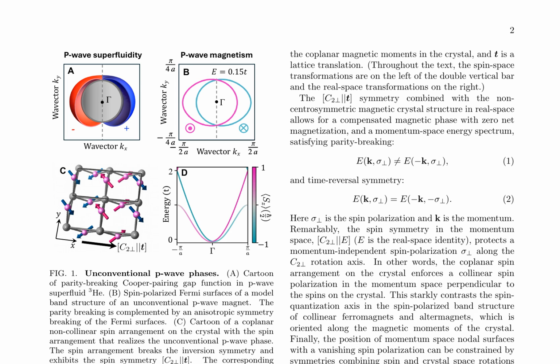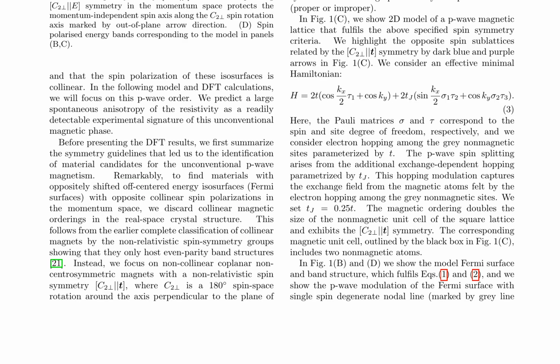To identify material candidates, symmetry guidelines are established, emphasizing the necessity of noncollinear magnetic orderings and non-centrosymmetric crystal structures. A model Hamiltonian is presented for the p-wave magnetic lattice, showcasing the crucial role of exchange-dependent hopping in inducing p-wave spin splitting. This model is carefully designed to satisfy the symmetry criteria, including the C2⊥||t symmetry, which protects a momentum-independent spin polarization. The ultimate goal is to predict a large spontaneous anisotropy of resistivity, a distinctive signature of this unconventional magnetic phase.